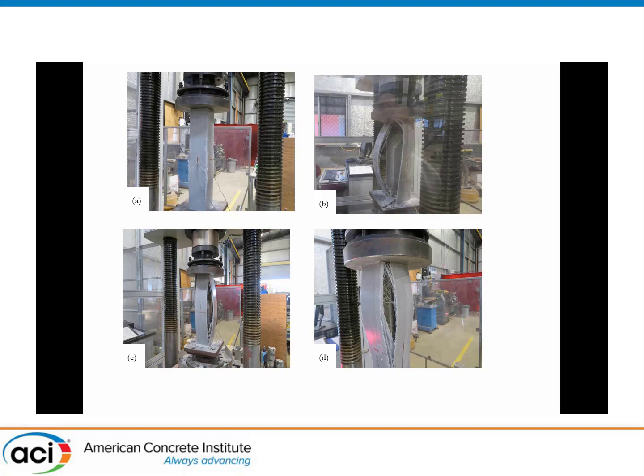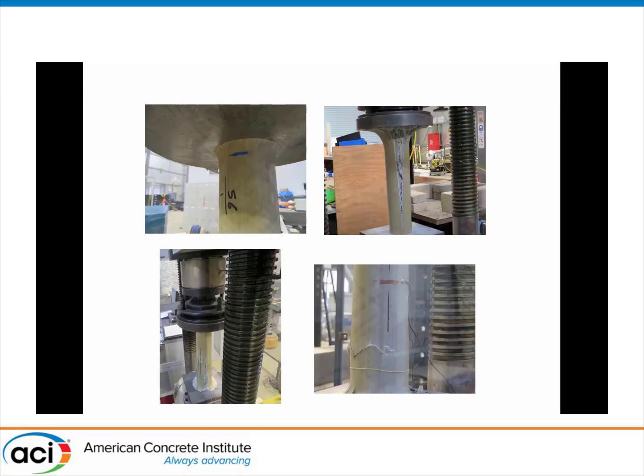And similarly, I'll show some figures here for the circular sections. You can see those fibers at plus minus roughly 56 degrees, and there are some more tightly wound ones around 70 degrees, and so on. There is no failure happening around the midsection, but it starts to load, and only at the very end you get failures at the top, and that's the ultimate failure we observe.